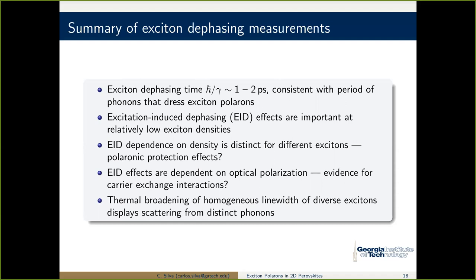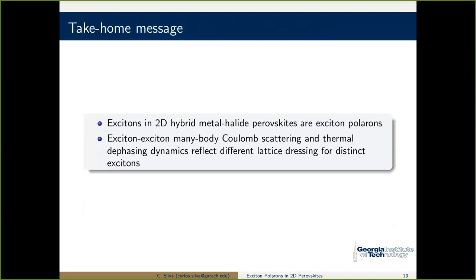I didn't show you polarization data. I did show you thermal broadening, but the fact that the exciton-exciton scattering leading to dephasing is unique for different excitons also is, I would say, a consequence of the exciton-polaron nature of these species.